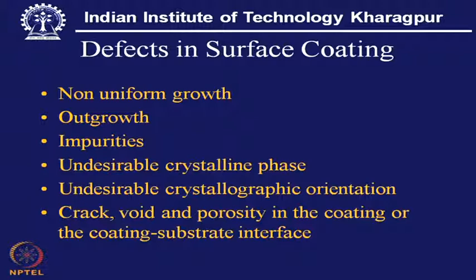Now comes the defects in surface coating. Now, what are those defects? Let us have a quick scan here. Number one, what we can see, a non-uniform coating. That means it has grown in a very non-uniform manner over the entire substrate, and depending upon some preferential sites, we have large growth, and in certain places it is very low growth.